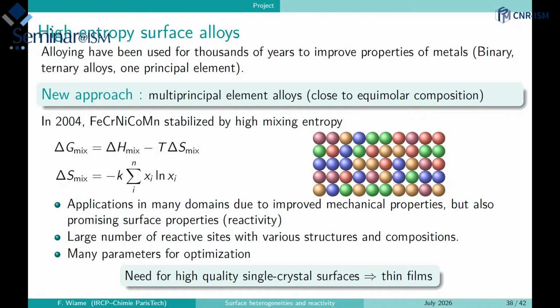So the mixing entropy will depend, obviously, on the relative concentration. If you have an equimolar composition, then you will increase the entropy. For example, if you imagine that you have 5 elements at 20% each, then the mixing entropy will be equal to log of 5, which is 1.6. And so relatively high entropy, which means that you can stabilize the total energy of your mixing by adding a large number of atoms.